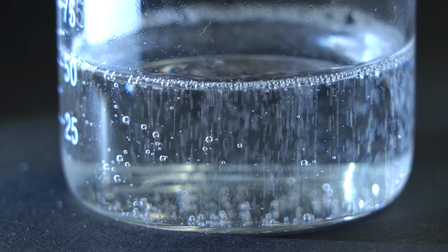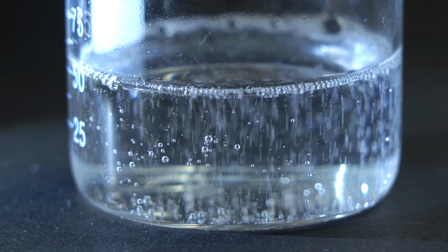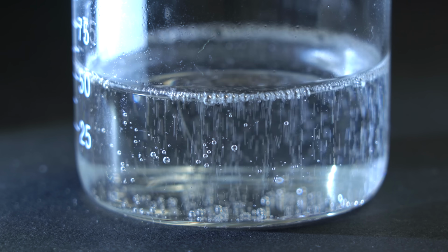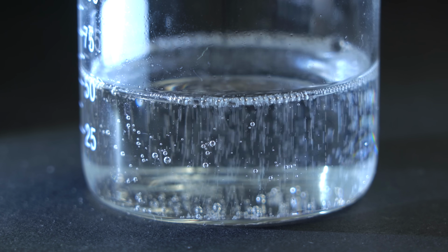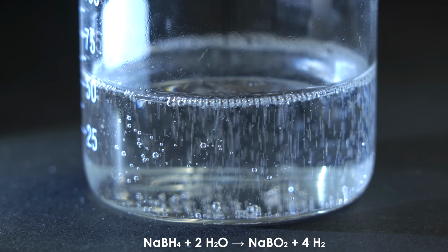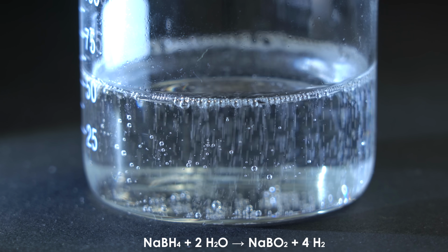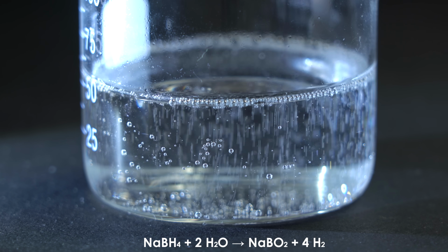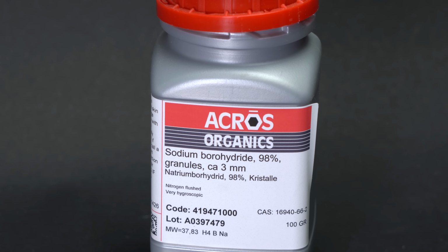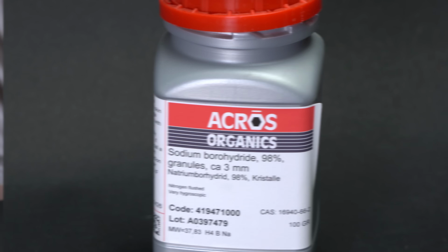It does it so easily that when dissolved in water, we can even see how bubbles are gradually being released from the sodium borohydride solution because this chemical isn't stable in water and quickly breaks down. In some recent researches, scientists even claim that this chemical can be used as a compact and effective preservative of hydrogen instead of gas cylinders, but only in the form of dry powder.